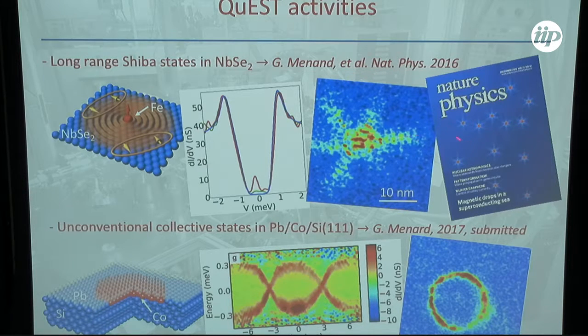It is one of the longest length scales of Yu-Shiba-Rusinov states, which allows, if you put impurities closer to each other, to braid them and work out. So here, what we did is another system. It's one monolayer of lead, and there is a cluster of cobalt beneath this, and you get again a very sharp band of Shiba states, and these bound states, as I told you, correspond to two peaks in